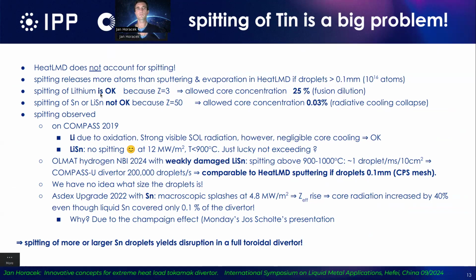This is not a problem for lithium because it has a very low atomic number, 3. So the allowed concentration is 25%. It just dilutes the fusion power. But for the case of tin, it's a very big problem because it has a huge atomic number. It means only 0.03% concentration is allowed in a tokamak. Otherwise, it would go to radiative cooling collapse of the plasma, in other words, thermal disruption.